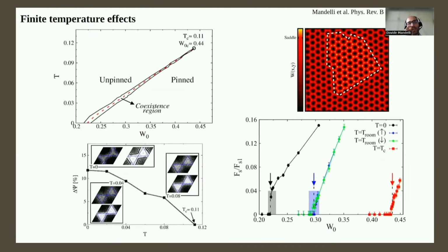We also tested finite temperature effects, and we found that this first order transition persists also at finite temperature. We studied the phase diagram here as a function of temperature and substrate corrugation potential. I'm using W here, but this is the same as U in the previous slide. There is a coexistence line that separates the superlubric or unpinned state at high temperature and low corrugation from the pinned state with finite static friction at low temperature and high corrugation potential.